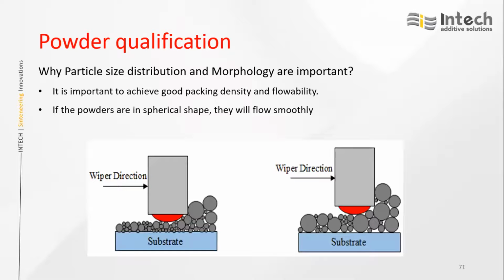Why are PSD and morphology very important? You can see when the powder is spread onto the plate, if a wider distribution is there, the packing is good - there are no pores in the left side image. In the right side image, you can see bigger particles with very few smaller particles, leaving gaps in between. If gaps are there, after printing those gaps will appear in the printed component, causing the powder density to come down. So powder selection is also very important.